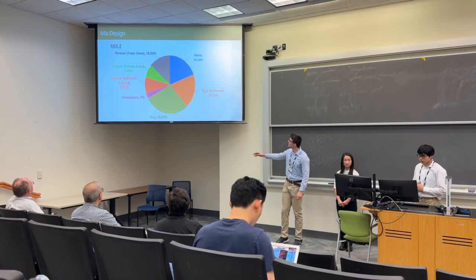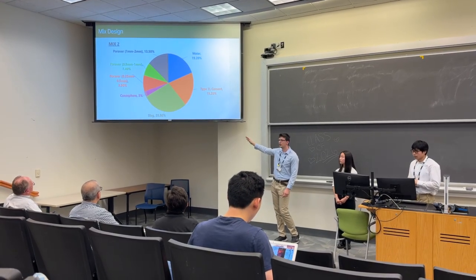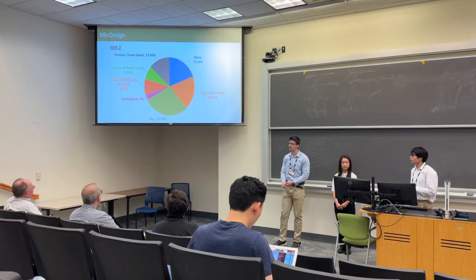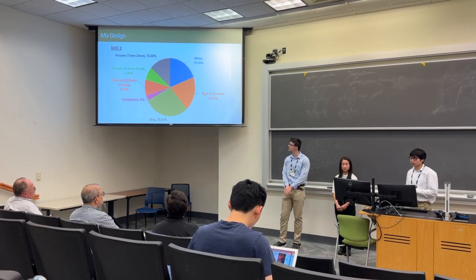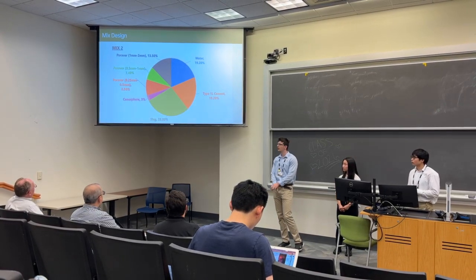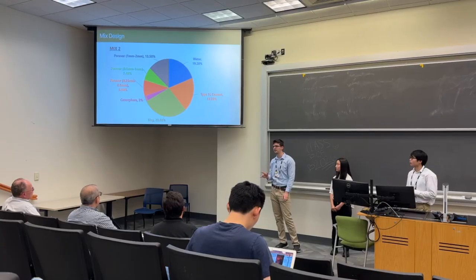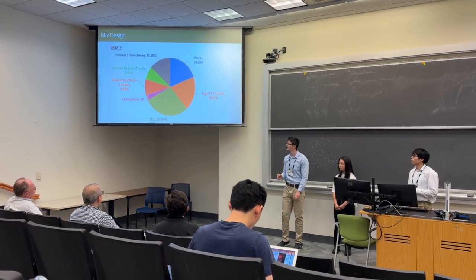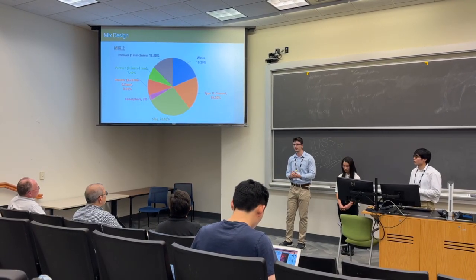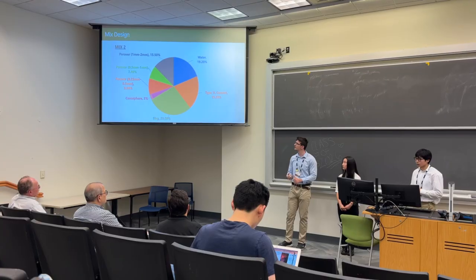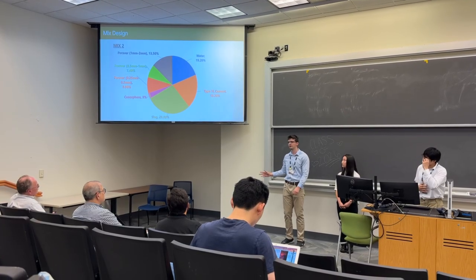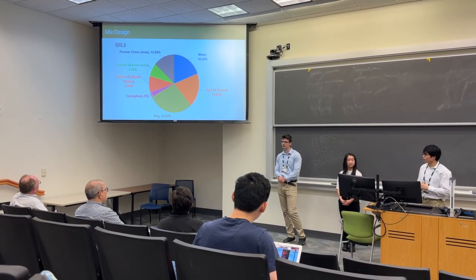Mix 2. The main difference between mix 1 and mix 2 is that there is no coarse aggregate in mix 2. All the aggregates consist of light aggregates, which greatly lowers the density while reducing the strength. This is compensated for by having a 3-layer canoe, with the first layer consisting of mix 1, and then the second and third cement layers consisting of mix 2. This will lower the total density of the canoe and allow it to be buoyant.